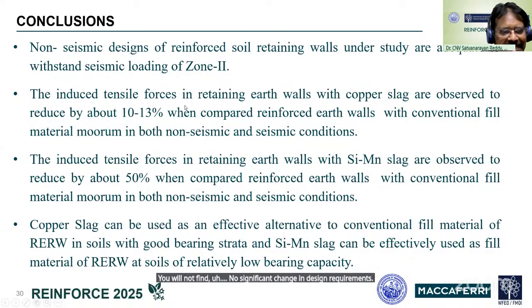The induced tensile forces in reinforced retaining walls with copper slag are observed to reduce by about 10 to 13% compared to reinforced walls with conventional fill material Morum in both seismic and non-seismic conditions. Similarly, coming to silicomanganese slag, the reduction in induced tensile forces was up to 50%.